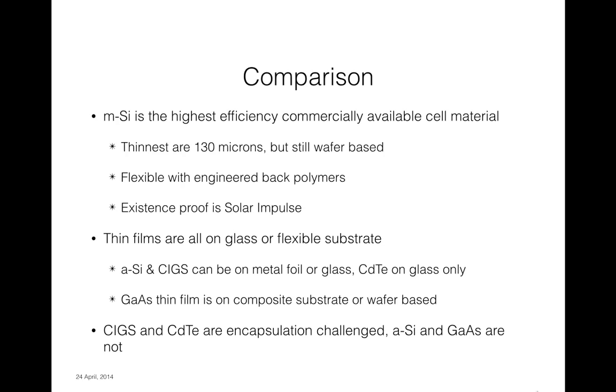CIGS and CdTe are encapsulation challenged. Environmentally, both of those materials are susceptible to moisture incursion, so you have to go to great efforts to seal the material against it. Even just common PET films are not good enough to cover CIGS cells. They will absorb moisture rather quickly, and you'll see a dramatic degradation in performance. The material does not like to be hydrated.